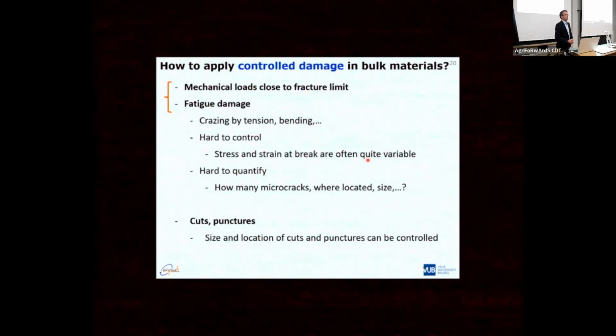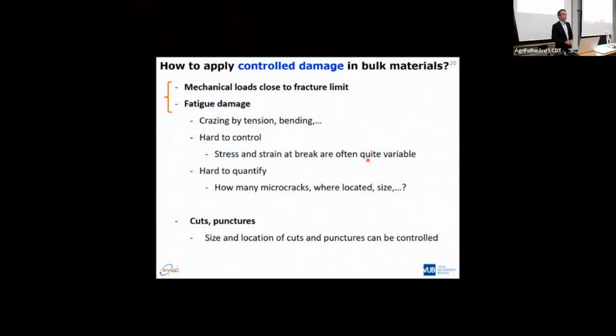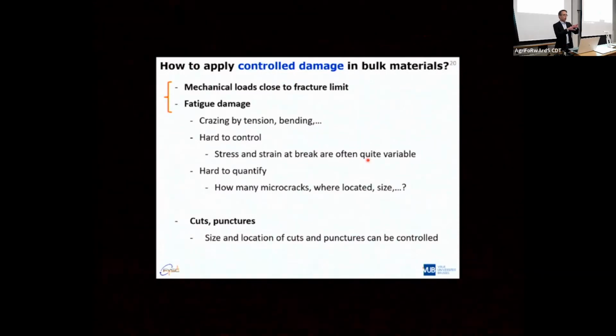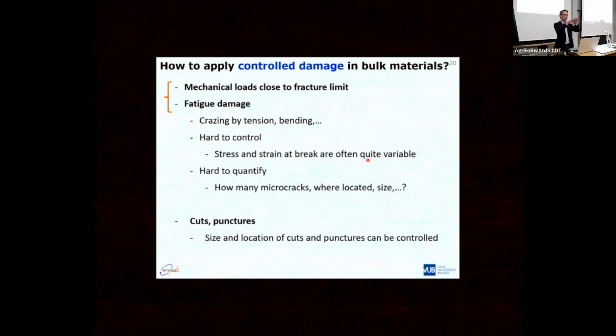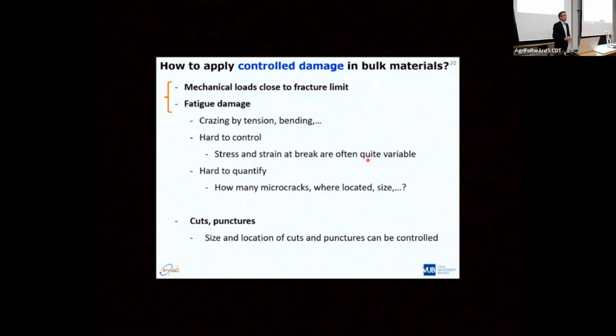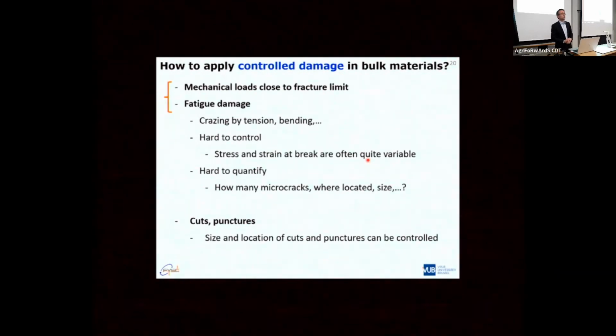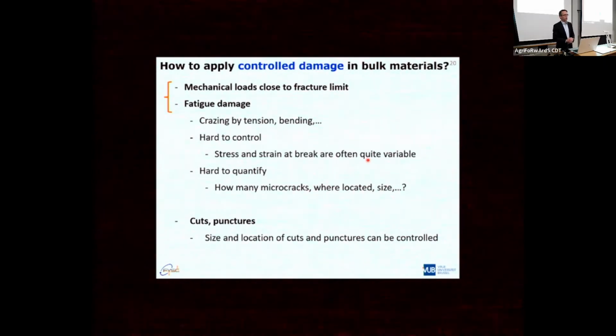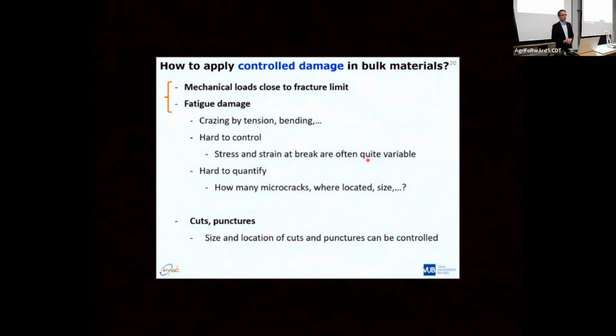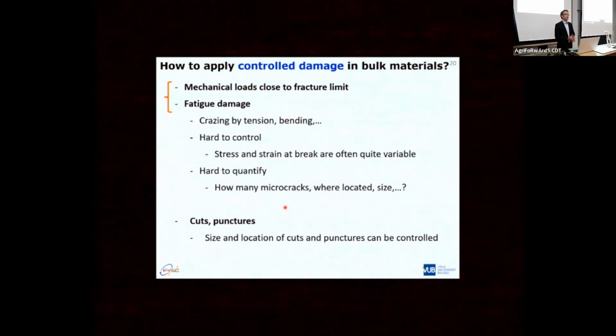What can you do? Okay, you can induce things like cracking by tension or by bending. You can always take the same radius of a bar, fold it over the same angle, and make sure then that you do it with a large enough number of samples to get, let's say then, reasonable averages or a reasonable statistical evaluation of what you are trying to do. It's very difficult to quantify in the samples how many microcracks there are, where they are located, and what their size is. There are ways to do it.